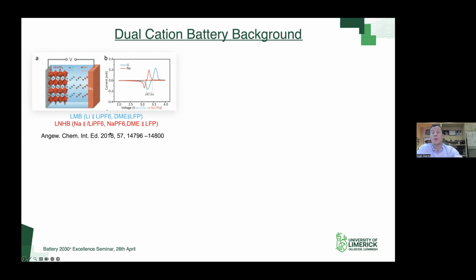So this is a paper which is reasonably old in this space. They were looking at an LFP cathode versus a sodium counter electrode, and the influence of these mixed electrolyte systems. This was a communication article in 2018, so the mechanism wasn't fully investigated. What they saw in this mixed system, in the red one down here, is a voltage shift that is just due to the fundamental potential difference between lithium and sodium. But they saw in their sodium hybrid system that they had more reversible cycling, so longer capacity retention.